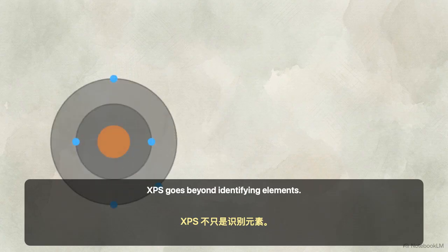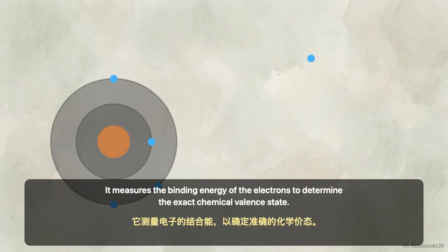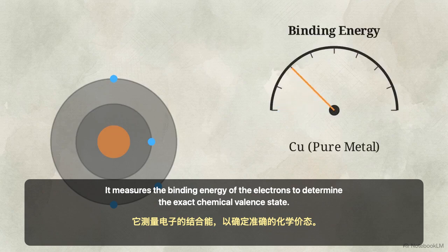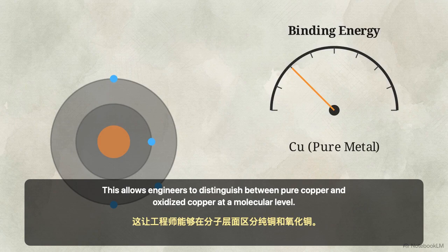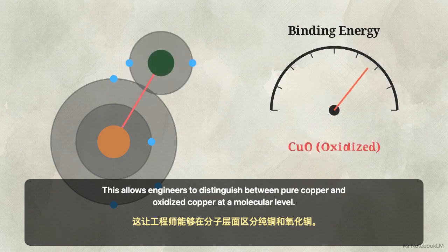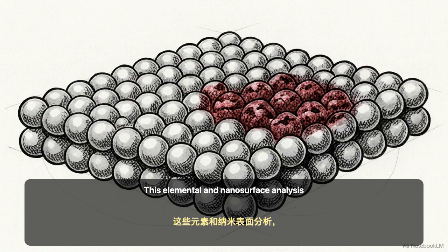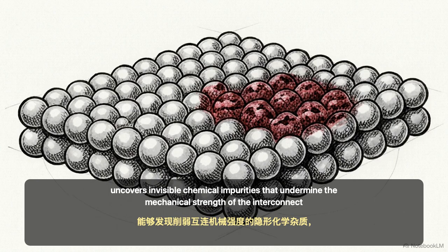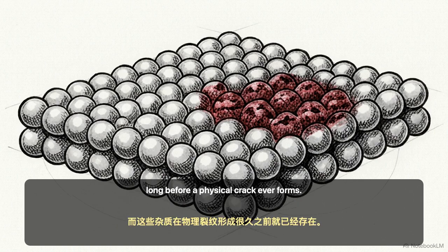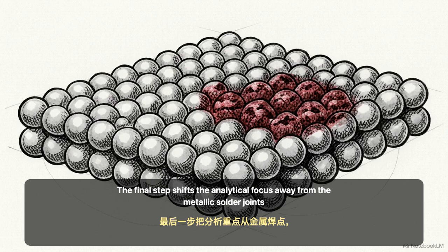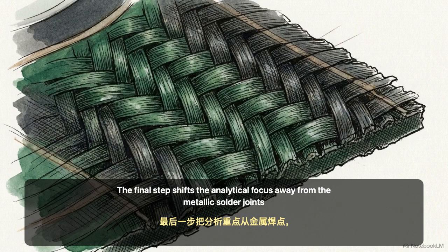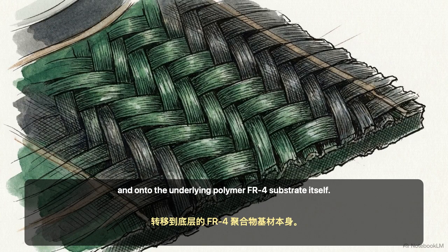XPS goes beyond identifying elements. It measures the binding energy of the electrons to determine the exact chemical valence state. This allows engineers to distinguish between pure copper and oxidized copper at a molecular level. This elemental and nanosurface analysis uncovers invisible chemical impurities that undermine the mechanical strength of the interconnect long before a physical crack ever forms. The final step shifts the analytical focus away from the metallic solder joints and onto the underlying polymer FR4 substrate itself.